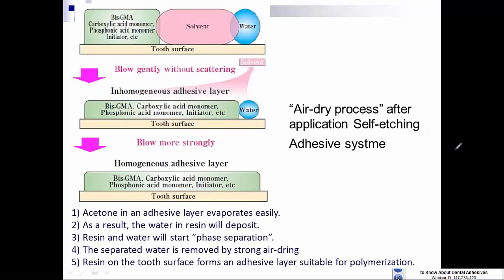Now one of the nuances about this, we're trading with self-etching adhesives less complexity about understanding moist dentin, because we don't have to worry about dentin moisture for these systems. But the drying step must be handled carefully, because there are acetone or alcohol solvents with water and high molecular weight monomers. The initial drying step for these materials should be gentle, so that we do not literally blow the adhesive off of the tooth and onto the tissue. That initial blowing gets off the volatile solvent and then creates the water and acidic monomer mixture, in which we can blow a little bit more vigorously to remove that excess water.